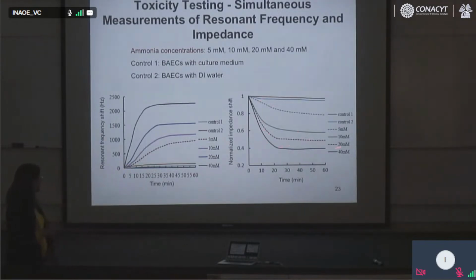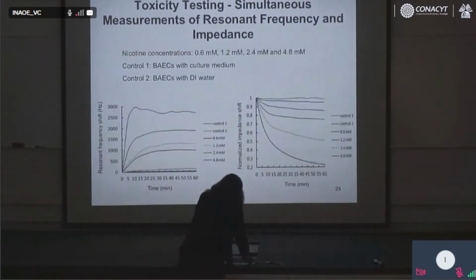We were surprised that we got, of course, the same result for the impedance spectroscopy, where the impedance is getting to lower values when the cells are dead. And here you see the impedance is decreasing after the same 20 minutes. The impedance changes the values.